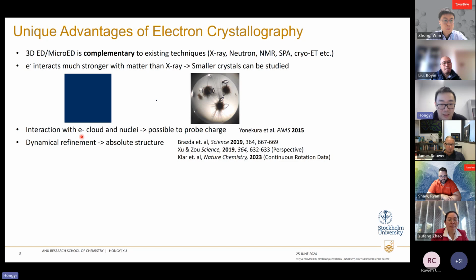Right, but nowadays, especially Lukas Palatinus's group in Czech Republic has developed this dynamical refinement procedure, so that we can treat the intensities we measure and solve the structure, and calculate the dynamical intensities from the structure models and compare with our experimental data. So this makes everything much more accurate. And then by using the dynamical refinement, we can actually tell the absolute structure of the molecule. So this will be very useful for the pharma industry also.